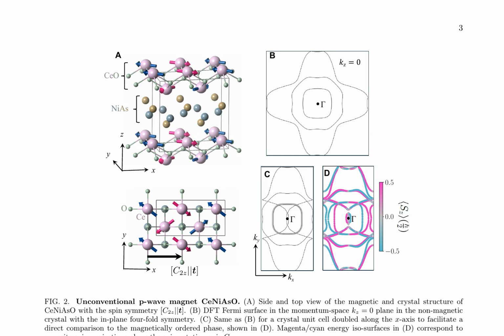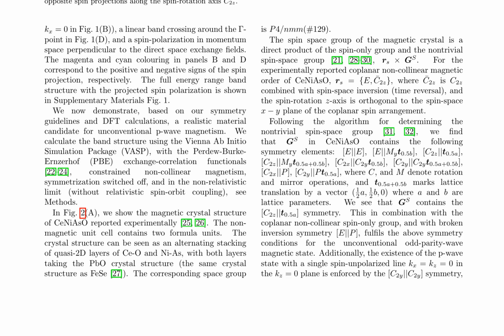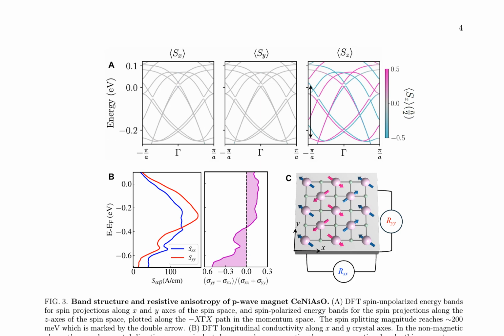The research paper discusses the unconventional p-wave magnetism in CeNiAsO, a material candidate with a realistic band structure and resistive anisotropy. The magnetic crystal structure, reported experimentally, features an alternating stacking of quasi-2D layers of CeO and NiAs, with both layers taking the PbO crystal structure. The spin space group contains the C2z||t(0.5a) symmetry, fulfilling the symmetry conditions for the unconventional odd parity wave magnetic state. The existence of the p-wave state with a single spin unpolarized line kx = kz = 0 in the kz = 0 plane is enforced by the C2y symmetry.